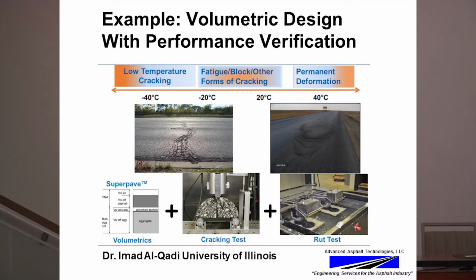This is the approach being taken in Illinois. So down at the bottom, what you have is the volumetric properties. So you're going to design the mix using current volumetric analysis. Then you're going to run two tests: the Illinois semicircular bend test, the IFIT, to look at cracking resistance, and the Hamburg wheel tracking test for rutting resistance. And Illinois is in the process of putting together criteria for those two tests for their conditions. This is work that was done at the University of Illinois by Professor Al-Qadi.